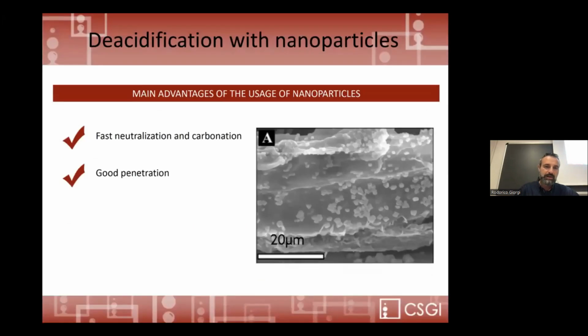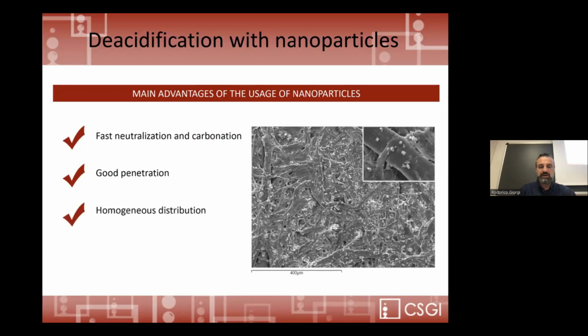And so the pH control is the sensitive point to inhibit in a very good way the degradation of cellulose-based artifacts. We do that using alkaline earth hydroxide dispersed in low polar solvents, low or medium polar solvent like alcohol. Why do we use nanoparticles? Because using nanoparticles, we have a very fast neutralization reaction and a very quick carbonation of the hydroxide that changes to carbonate. We obtain, thanks to alcohol, to low surface tension solvents, a good penetration and homogeneous distribution of particles.